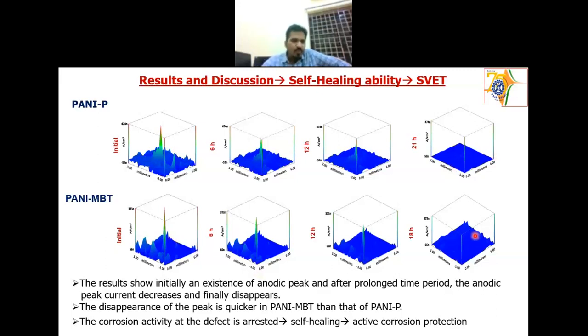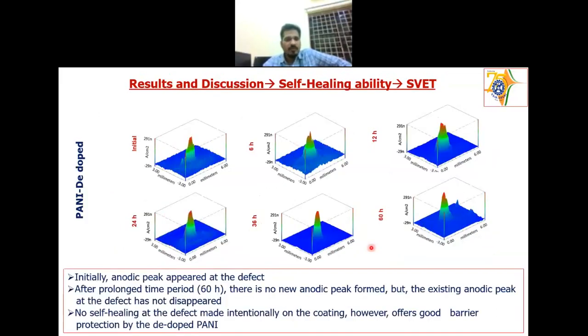That means when you add this Pani-based inhibitor here, it can heal the defect through a self-healing mechanism. Further, we did a dedoped one also. For the dedoped Pani, we put a defect here, but the dedoped case is only able to give barrier protection. It is not able to give any kind of active protection. That is why there is no diminishing of the peak here.